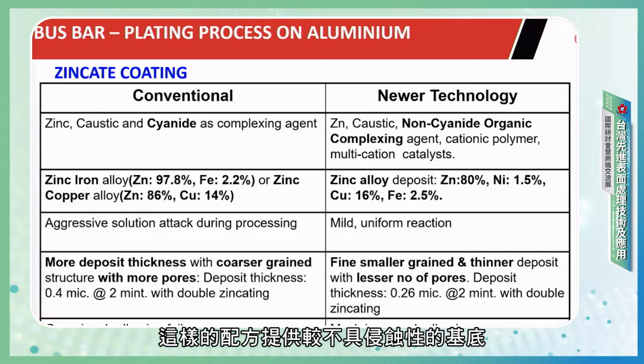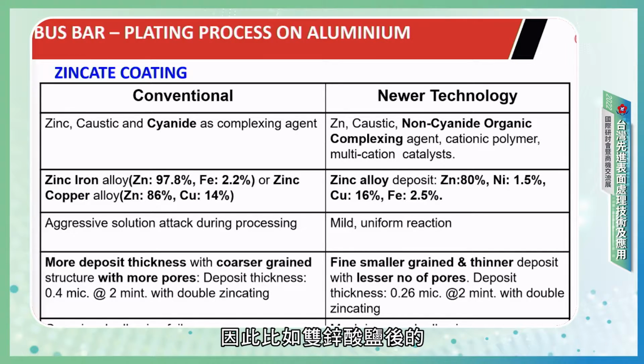It provides less aggressive attack to the base, and therefore the thickness of the zincate coating after double zincate is approximately 0.26 micron at 2 minutes of zincate coating. So it's a more thinner deposit and more compact, which helps for the subsequent deposit addition.